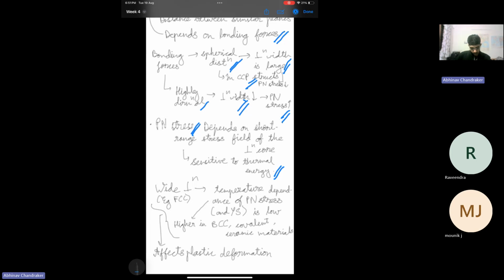Another point is that wide dislocations will have a lower temperature dependency of the PN stress compared to narrower dislocations. So as a result, these FCC alloys tend to have a lower dependency of PN stress on temperature.